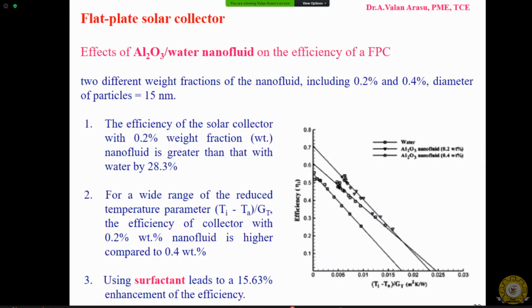So instead of water, Al2O3, a non-metallic oxide nanoparticle based water, is used, with different volumetric concentrations like 0.2% and 0.4%. Particle size is 15 nanometer. It is found that the efficiency of the solar collector is greater for the 0.2 percentage weight fraction compared to the 0.4 fraction. And further, when we use the surfactant, the efficiency is further increased.